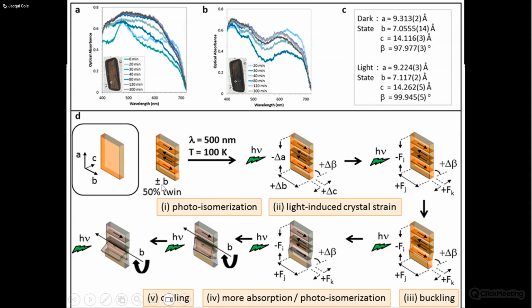So we think, so this is our photoisomerization. Remember, it's 50% twin, so that's plus and minus in the B direction, right? So that's quite important. And the twinning therefore gives it the option to be, you know, some arrows this way and some arrows that way. And then as light keeps building on, you get this crystal strain effect. And of course, that's manifested in this buckling effect, and these are the sort of various forces that you would expect to be on it.